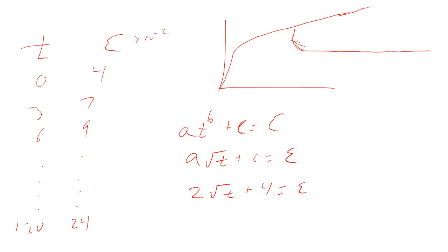Again, the curve fit doesn't matter. As long as you have something that decays, you didn't even have to fit it. You could just have written, it's linear viscoelastic, so it has to decay. We're just going to assume that it decays to 0 at 200 minutes or something like that, and that would have been more than enough. Or you could have sketched the graph with the appropriate drop, and the superposition, and that would have been more than enough.